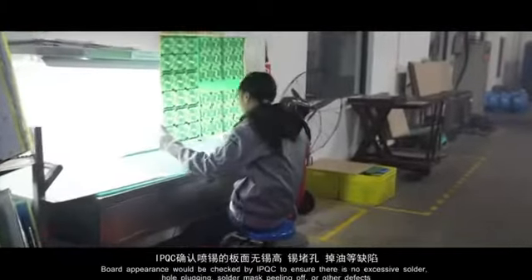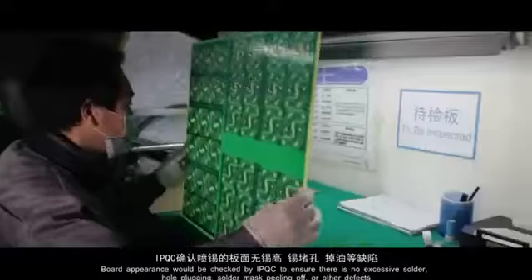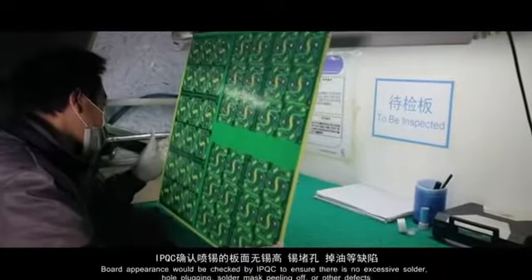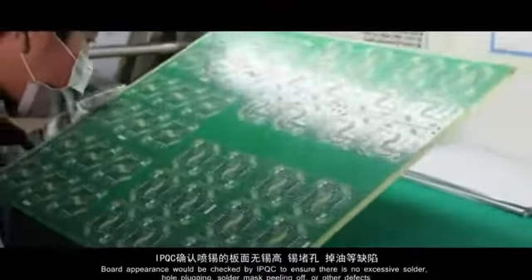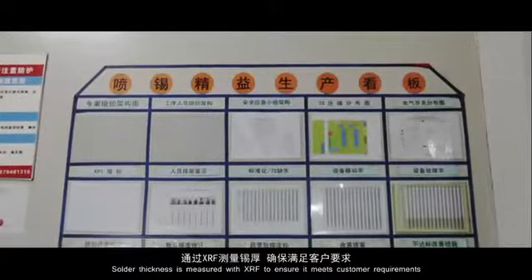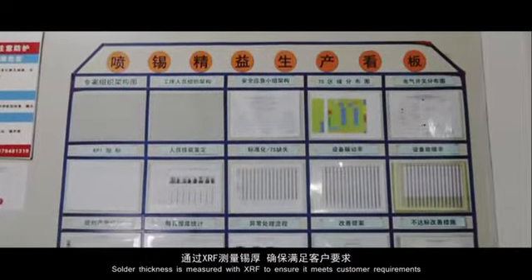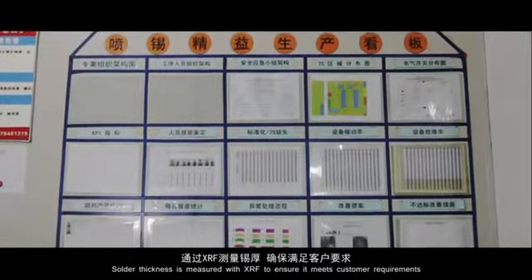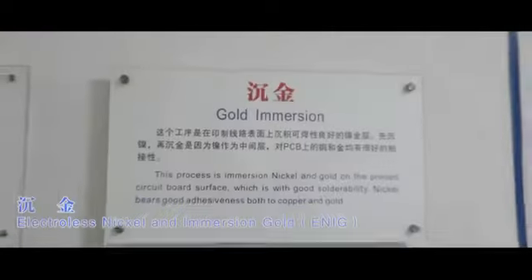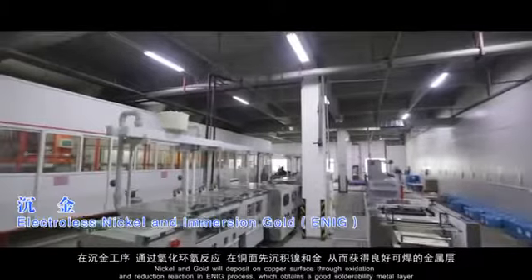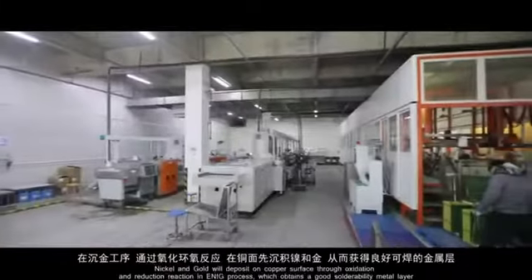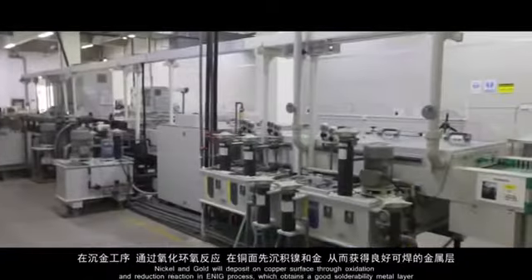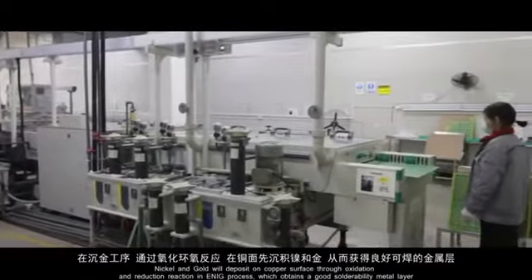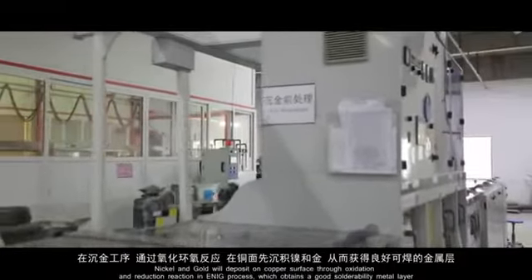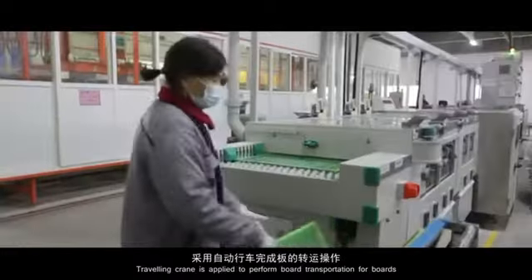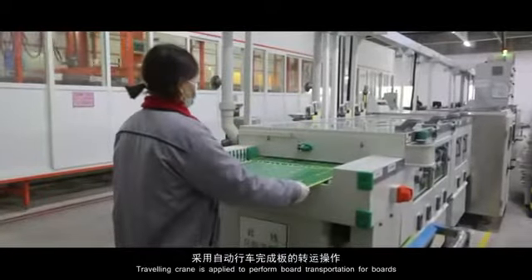Board appearance would be checked by IPQC to ensure there is no excessive solder, hole plugging, solder mask peeling off, or other defects. Solder thickness is measured with XRF to ensure it meets customer requirements. Nickel and gold will deposit on the copper surface through oxidation and reduction reaction in the ENIG process, which obtains a good solderability metal layer. A traveling crane is applied to perform board transportation.